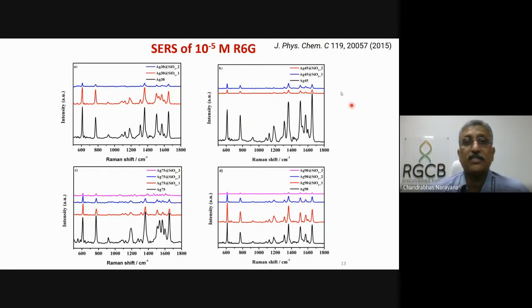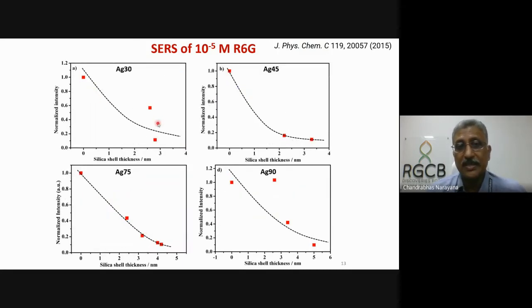We used the same concentration of R6G, and you can see to what thickness you are able to detect this Raman signal. As you can see, as you increase the size of the nanoparticle, you are able to go to thicker and thicker SiO2. If you plot it in a graph, you can see that if you have a smaller nanoparticle, the detection level is about 2.5. But as you increase the nanoparticle, your detection level keeps on increasing. For 90 nanometer silver nanoparticles, you can even detect up to 5 nanometers. So that is more realistic, and people have now understood that it is indeed very important that the size of the nanoparticle also matters.